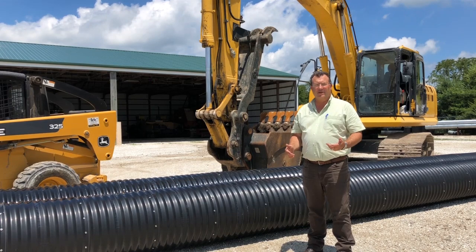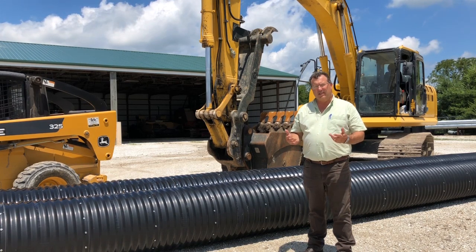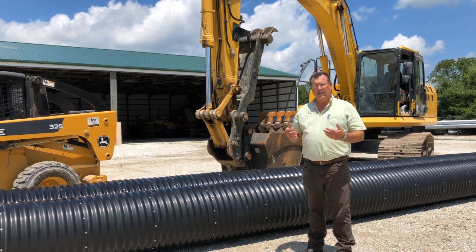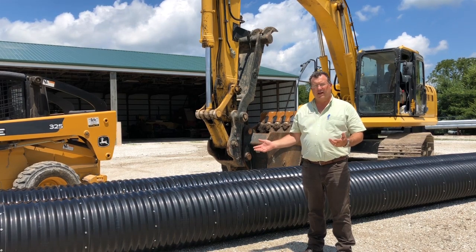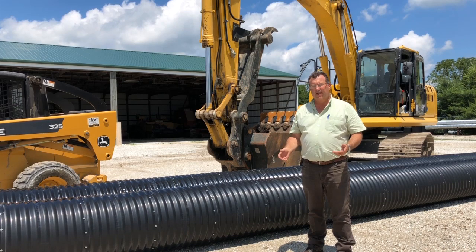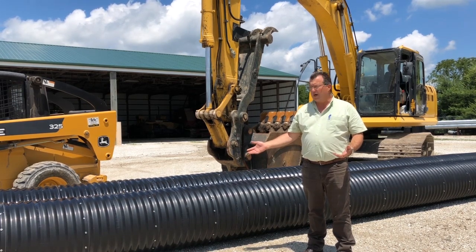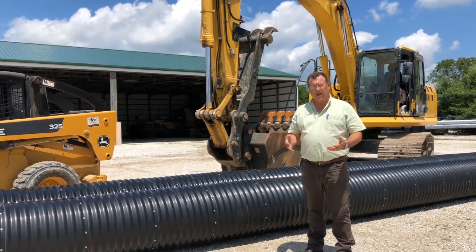My name is David Marth. I'm the County Engineer in Greene County, Illinois. I'm here to talk about polymer coated galvanized pipe. We've been using the pipe for 18 years. We started experiencing less than desirable service life due to subsurface drainage in the agriculture area — we have a lot of subsurface chemicals that come through the drain tiles. We looked at various Federal Highway Administration circulars and empirical testing and were impressed with the estimated service life from polymer coated galvanized. As a result, we started using it, and now use all polymer coated galvanized at all of our crossroad locations. All the pipes that we've put in over the last 18 years still look essentially like the new pipes that we're installing today. We're very happy with the performance, the ease of installation, and all the overall characteristics of the pipe.